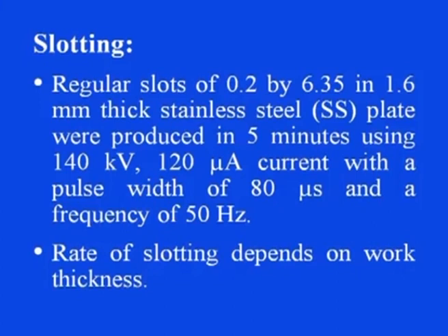Another application is slotting. Regular slots of 0.2 by 6.35 inches in 1.6 millimeter thick stainless steel can be produced in 5 minutes using 140 kilovolt, 120 microampere current with a pulse width of 80 microsecond and a frequency of 50 hertz. This has been reported by researchers.